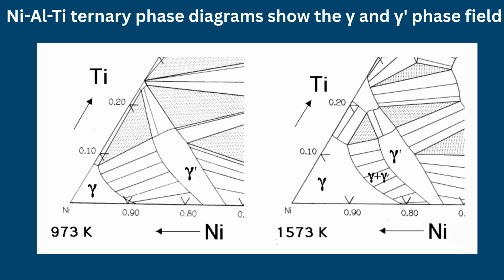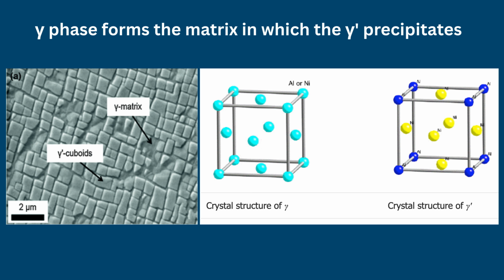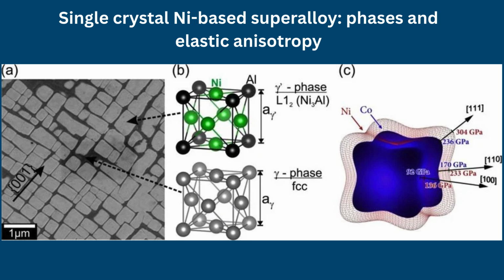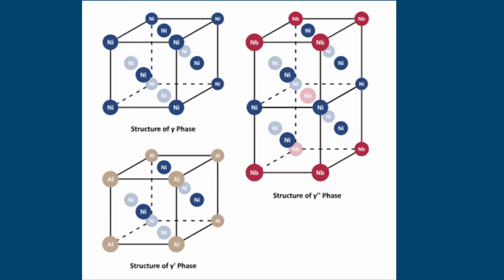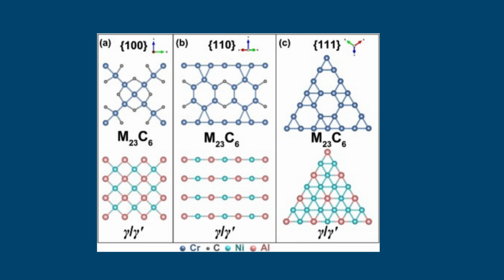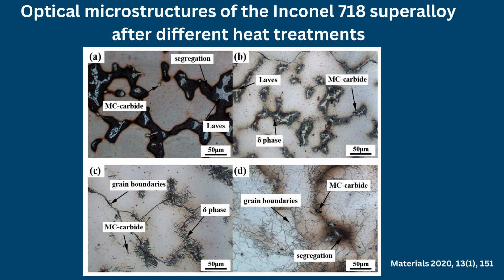Their exceptional performance originates from a predominantly FCC gamma-nickel matrix, strengthened by alloying elements such as chromium, cobalt, molybdenum, tungsten, and rhenium. The most important strengthening phase is the ordered gamma prime phase, nominally Ni3(Al,Ti), which possesses an L12 structure and remains coherent with the gamma matrix. In some alloys, particularly IN718, the ordered gamma double prime phase, approximately Ni3Nb, provides major precipitation strengthening. Carbides such as M23C6, M6C, and MC can additionally contribute to grain boundary and matrix strengthening.